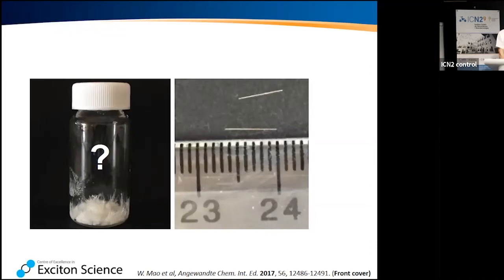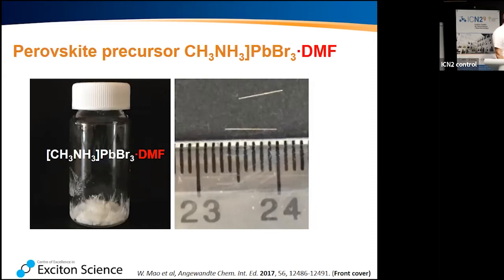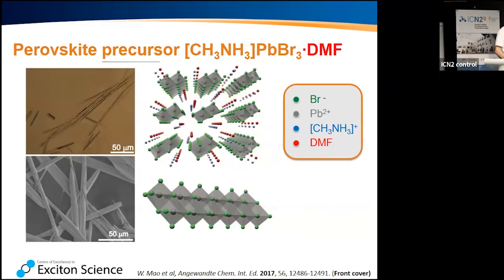Yeah, we also were puzzled for a bit. So that's a millimeter scale. We get several millimeter long needles. So this is the one we had. So we actually had a one-dimensional kind of perovskite-like structure, and that was methylammonium lead bromide with the DMF solvent integrated into it. And this is an animation that shows a little bit. So you have these double columns of your perovskite octahedra, PbBr6 octahedra, that form these 1D structures.